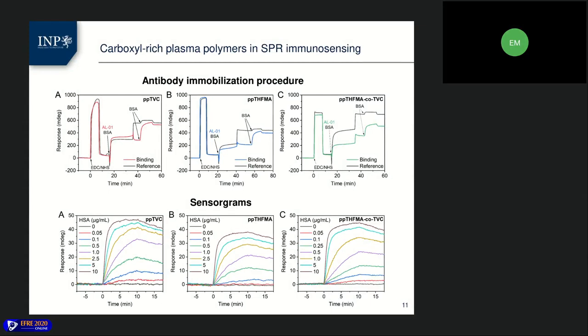SPR immunosensors using all three types of the obtained films were developed. The procedure for immunosensor preparation remained the same, except that the SPR slides were inserted into the SPR setup after the stabilization step, immersion in water. The activation, antibody binding, and blocking steps were carried out online, and sensorgrams of the sensor preparation procedure were recorded.